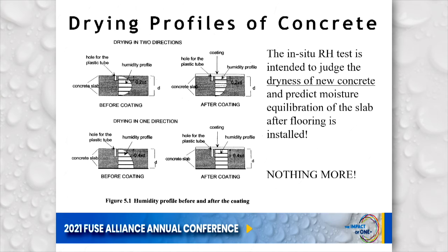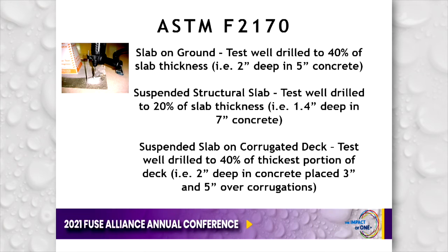If we use it for other things, we need to consider other factors, and that's the big thing I want to get across to everyone. So ASTM F2170, again, says that those test wells are to be drilled to 40% of the slab thickness. That's 2 inches deep in 5 inches of concrete. On a suspended structural slab, which we didn't talk about, this is concrete drying from both sides, that test well should be drilled to 20% of the slab thickness. These are typically thicker slabs, so I can say an example, 1.4 inches in a